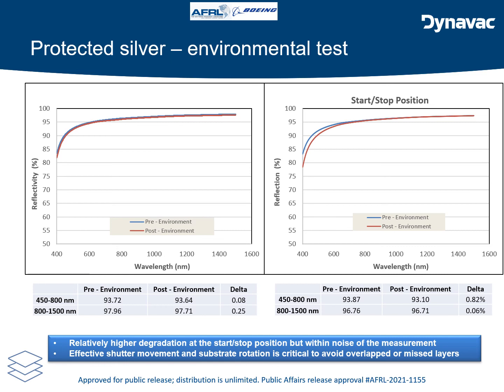As we can see in the plot, there was a mild change around the visible regime, but it is pretty insignificant considering the noise factors in the measurements. This tells us that the shutters worked precisely and well enough that we don't see noticeable change along that strip.